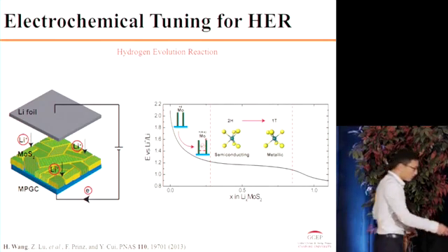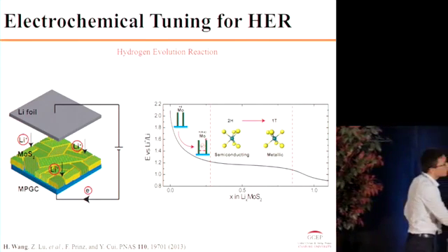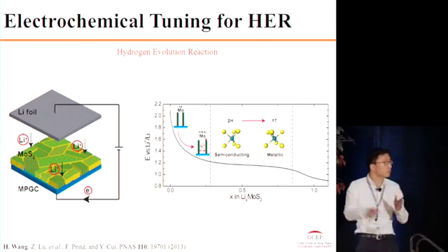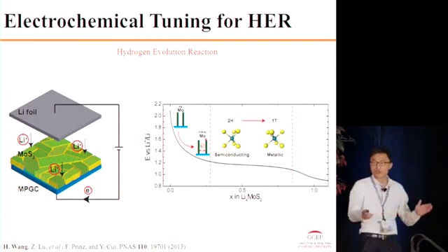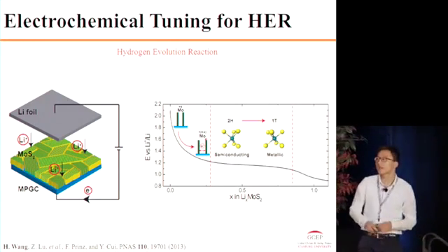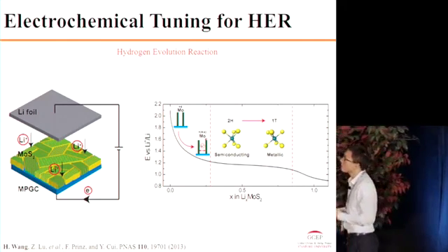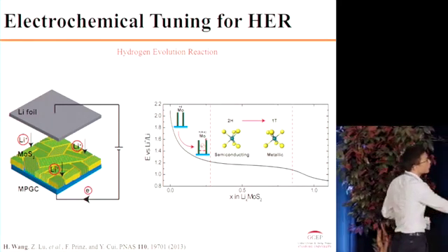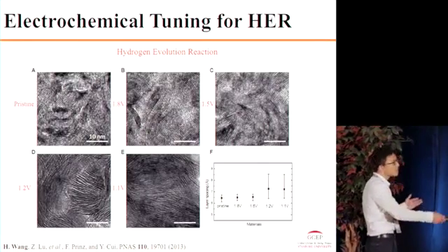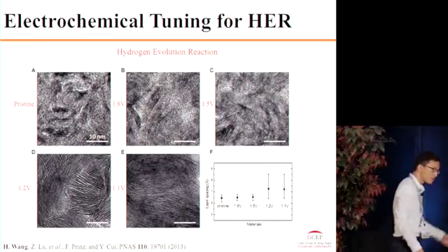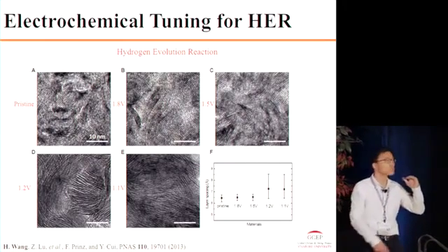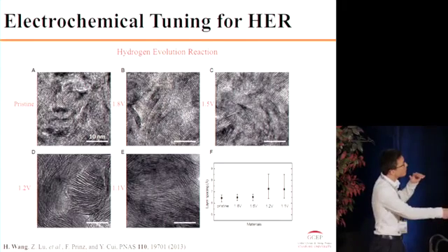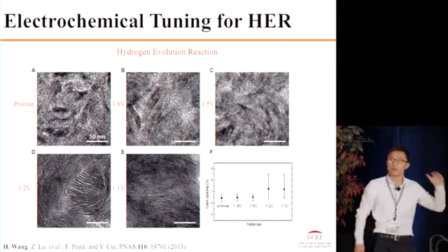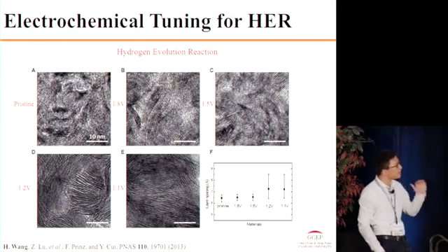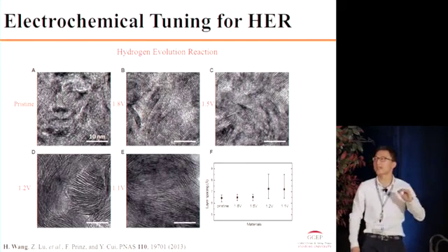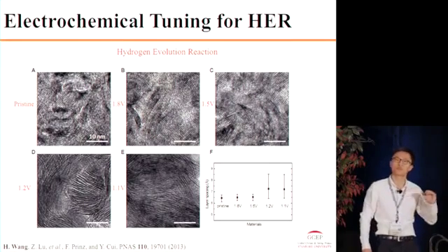And this lithiation plateau represents a very good, well-defined phase transition from the 2H semiconducting phase to the 1T metallic phase. And also, there might be a lot of changes during the lithiation process, so we stop the lithiation voltage at 1.8, 1.5, 1.2, and 1.1. We stop at each potential and take the sample out to examine what happened to these samples.